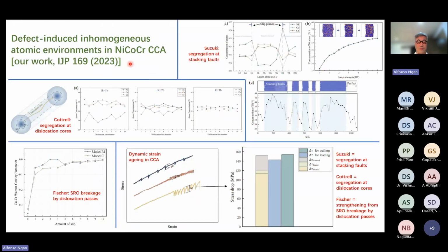So this was a paper we published a few years back, and this just illustrates the type of defect-induced atomic environments in this case a medium entropy alloy, involving three elements: nickel, cobalt, and chromium. This is an FCC system, and the stacking fault energy is actually very, very low. So the a/2<110> dislocation would dissociate widely into two Shockley partials with a stacking fault in between. So we will obviously have Suzuki segregation, where if you look at this plot over here, which may be too small to be seen, but I'll tell you the result.